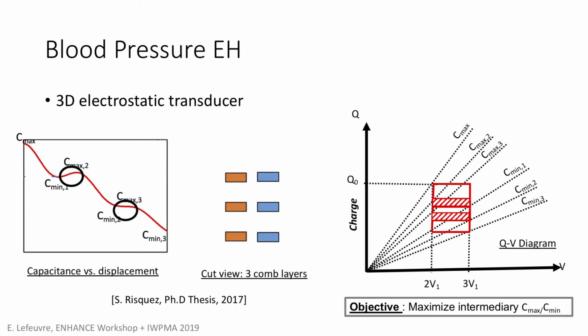Actually, this is the moving and fixed combs at rest. And when we move it, we have here the capacitance that decreases to a first minimum value. Then we turn to a local maximum, then to another minimum value, then to another maximum, and then to the last minimum value. So for the first one, we moved from this maximum to the first minimum, so we performed this beginning of cycle. Then we climbed up to this local maximum, and then we went down here. Okay, so we have a first loop. This loop here corresponds to energy that is harvested.